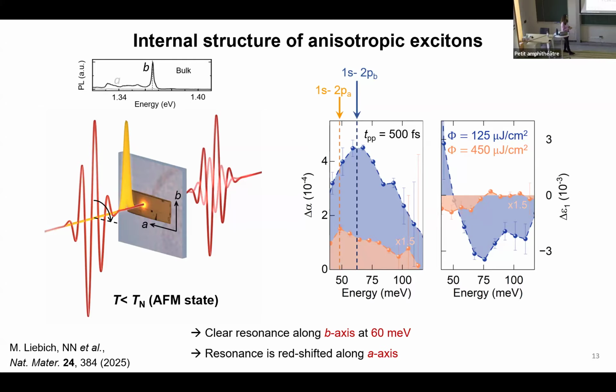And also we see that our resonance has shifted to lower energy. So there must be a degeneracy lifting between our orbitals. And this can be the 1s 2pA orbital transition. So it seems that due to a highly anisotropic dielectric function of chromium sulfide bromide, the degeneracy of excitonic orbitals